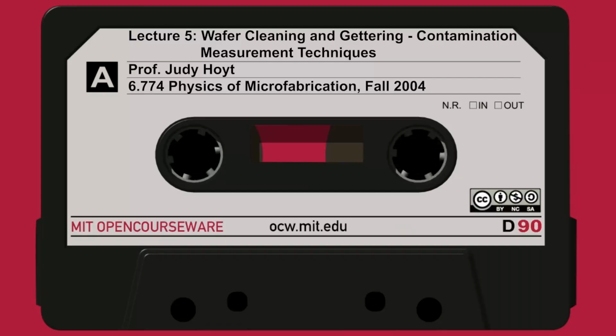Now let's go to region B of that curve. That's here under depletion in the center. When I'm depleted, the bias voltage again is a little bit closer to zero. I don't have as much band bending. And in fact, some of these interface traps are now filled with electrons, maybe about half of them. So the amount of QIT that's uncovered at that interface in this bias condition is less. So I have less interface trap charge. Indeed, if you look at the ideal curve and the distorted curve, at point B there's less of a shift than there was at point C, because there's less positive charge at that interface. And now let's finally go to accumulation.